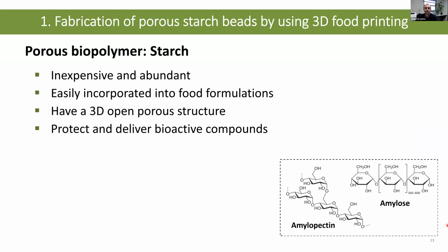So what we are proposing here is to use 3D food printing to encapsulate those compounds to increase their chemical stability as well as their bioavailability in the body once consumed. So one of the polymers we are using here is starch. And why are we using starch? Starch is inexpensive and abundant. It is really present in many food formulations, so you can easily incorporate it into foods. Another advantage is it creates a porous network without really using any crosslinker or chemicals. You can just heat it up and create a gel which has a porous structure, which can really protect and deliver bioactive compounds.